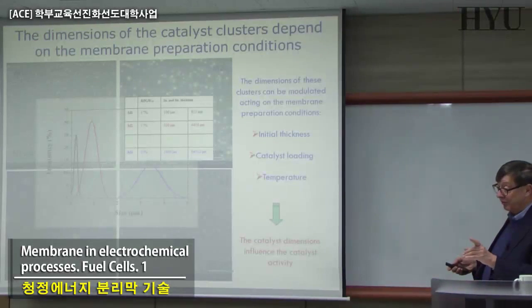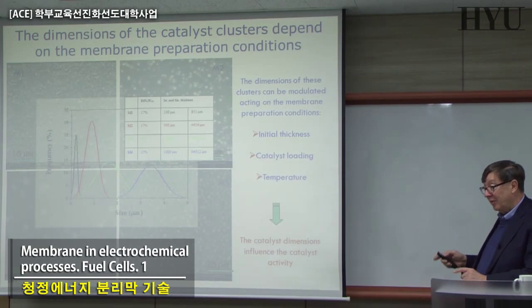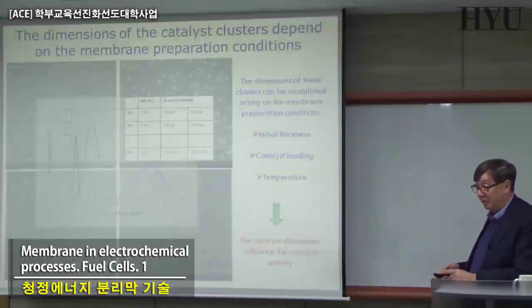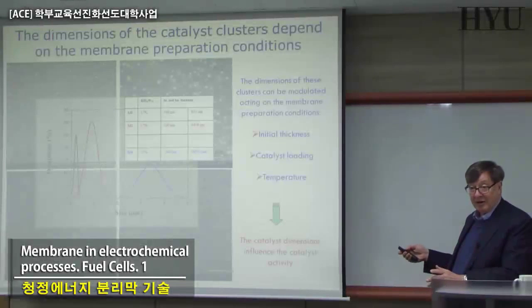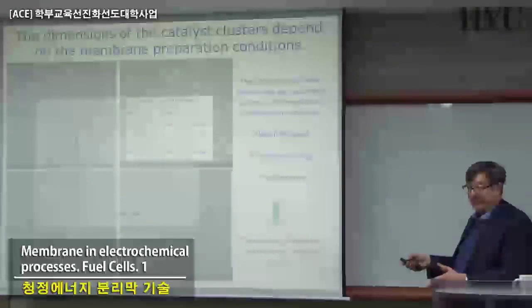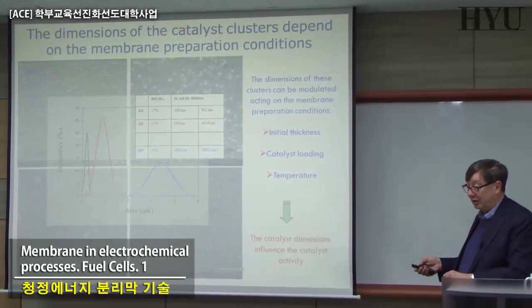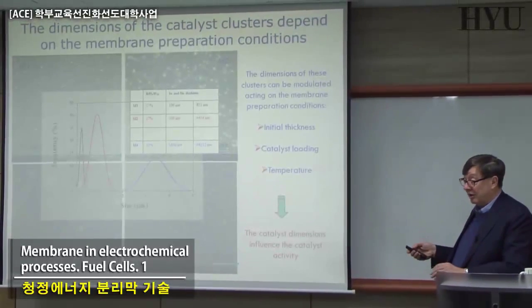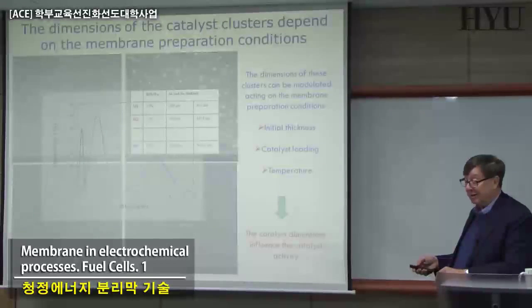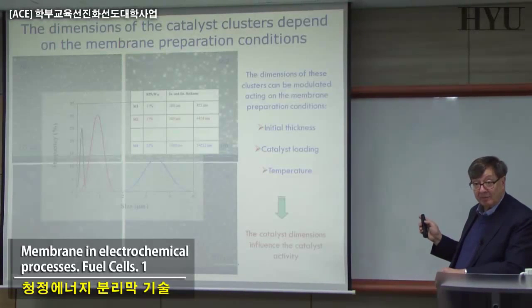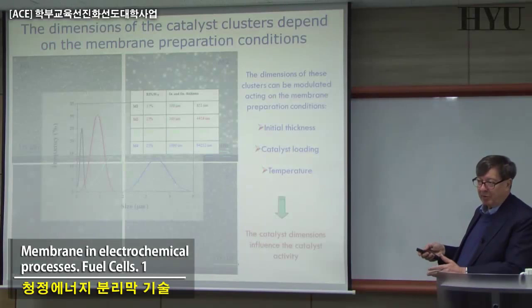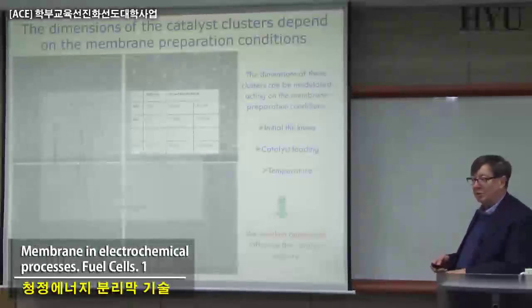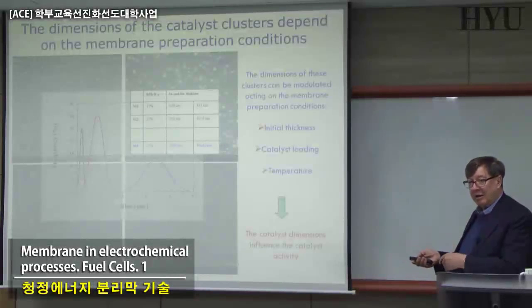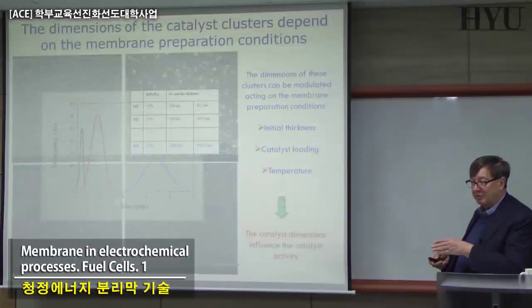And keep in mind, however, that after doing this, another very severe problem exists. Okay, very nice, and you start to work on it. You can change significantly the performance of your catalyst by changing the size of the droplets, which is in principle relatively obvious, because it relates to the amount of catalyst you mobilize. The problem of mass transfer is also related to the size of the droplets, obviously.